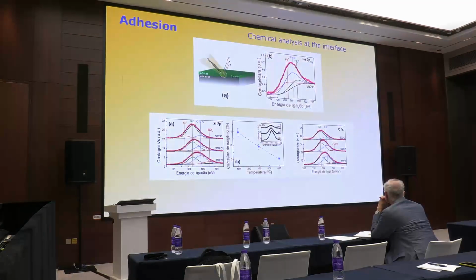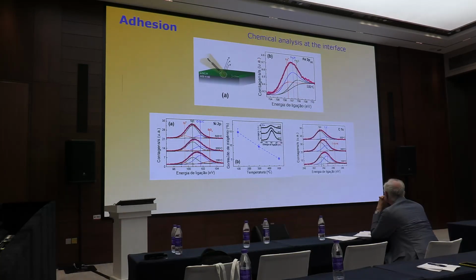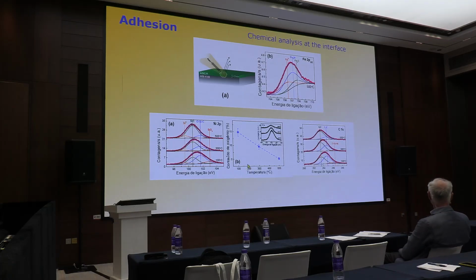But to finish, I would like to show you that when we analyze the interface or the interlayer of silicon carbide, this interlayer contains lower oxygen at higher temperature. And this is the origin of adhesion. We can improve the adhesion experimentally. Increase the temperature. What does it mean? That means that we remove more oxygen when we increase the temperature, and the adhesion improves due to less oxygen at the interfaces between the steel, the interlayer of silicon carbide, and finally the thin film of amorphous hydrogenated carbon.